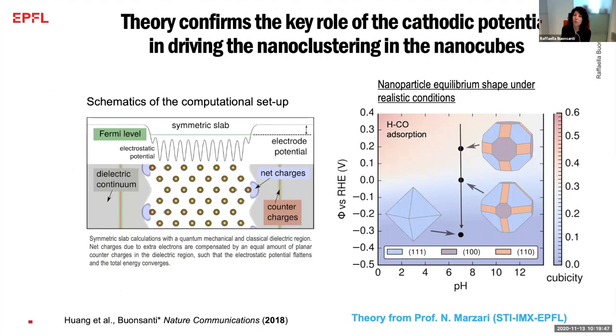In this case, we worked with another theorist and, together with a lot of control experiments, he helped us to elucidate the reason why the cubes change shape: the 100 facet becomes unstable when we apply such a negative potential. And so going forward, this means that if we are able to activate this catalyst at much lower potential, it will be stable.